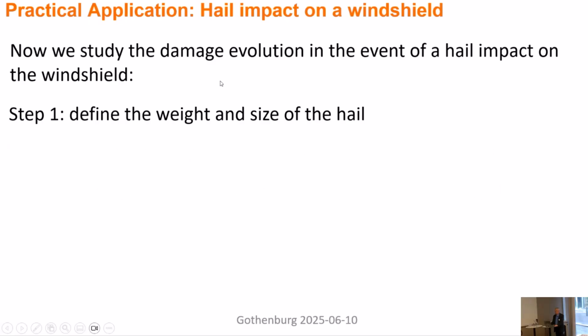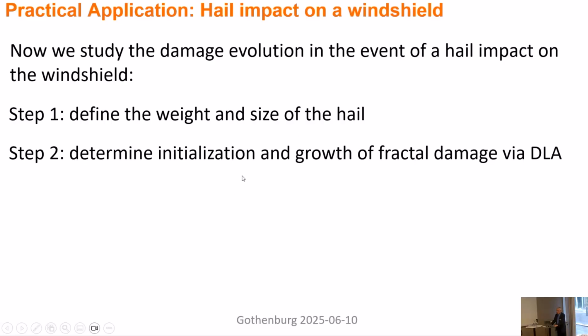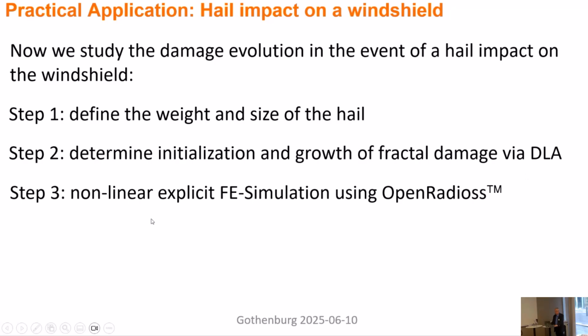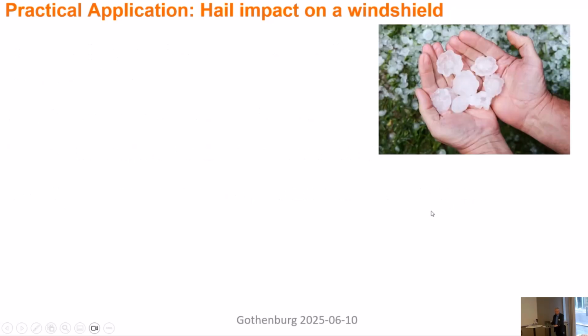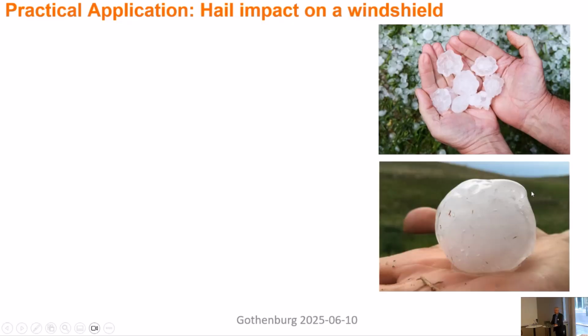So now we study the damage evolution in the event of hail impact on a windshield, define the weight and size of the hail, and determine initialization and growth of fractal damage via DLA, using nonlinear explicit FE simulation with OpenRadioss. And this is what we observed. These are hails, which we already observed. This is a photo from reality, but you can also have these guys here. These are a little bit more dangerous, but still observed in reality.